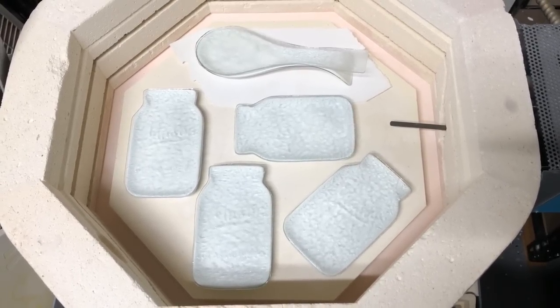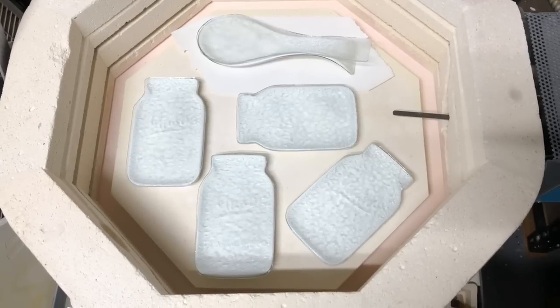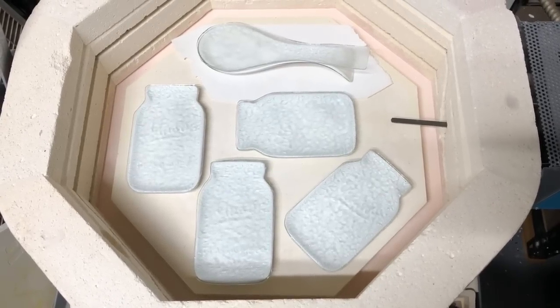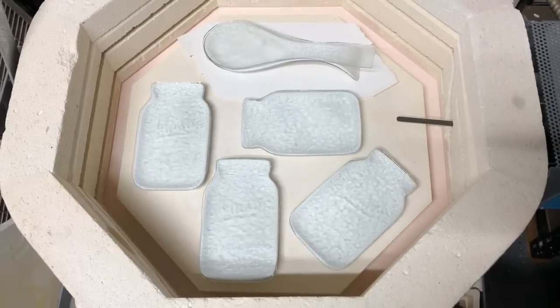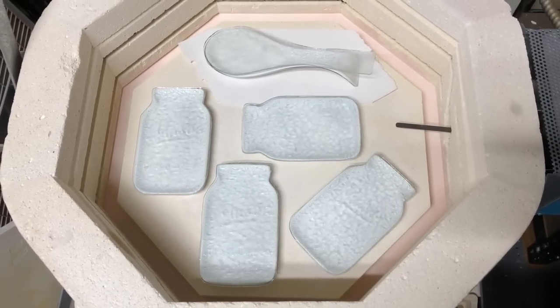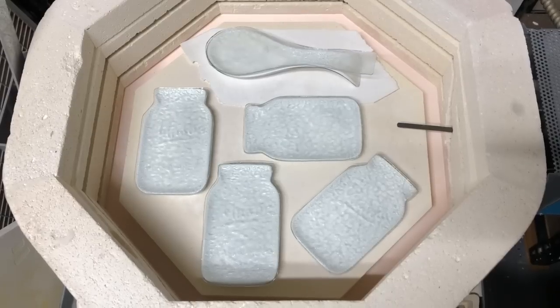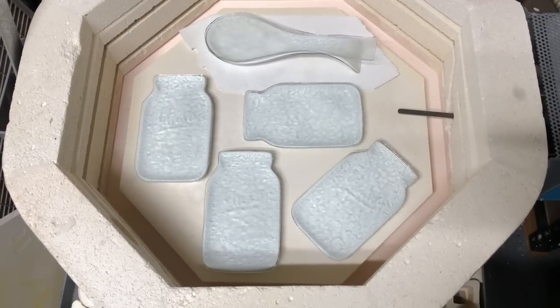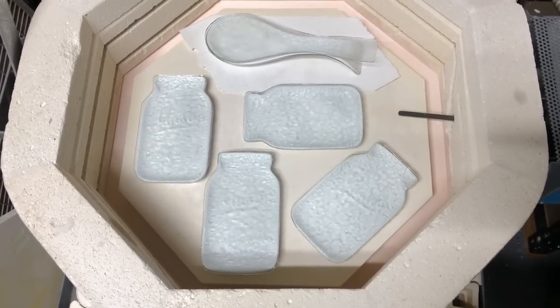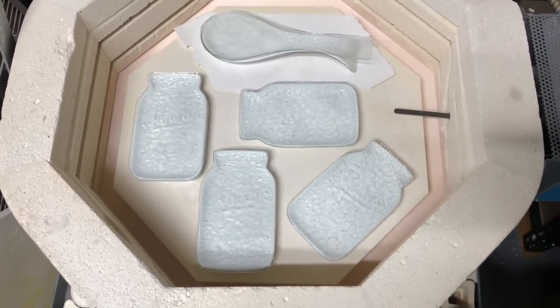Then I'll take it as fast as possible to 1500 where I'll hold it for 20 minutes. Then I'll take it as fast as possible down to 900, hold it for an hour. And then from there, I'll step it down 100 degrees an hour down to 600. So here we go. We'll give it a shot and see if this worked.